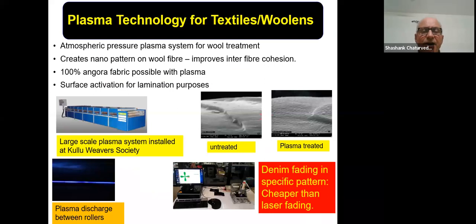Okay. Let me come to a very different application, that's plasma technology for textiles and woolens. We've developed atmospheric pressure plasma systems for wool treatment. Now, normally you might be aware that Angora wool, which is otherwise very warm, you cannot make 100% Angora fabric. That's because the coefficient of friction is very low. By creating a nanopattern on the wool fiber using plasmas, it improves the interfiber cohesion. So you can make 100% Angora fabric.